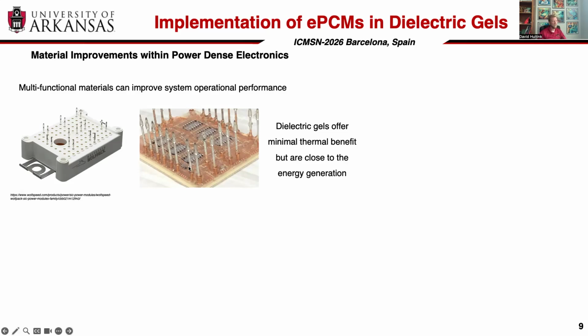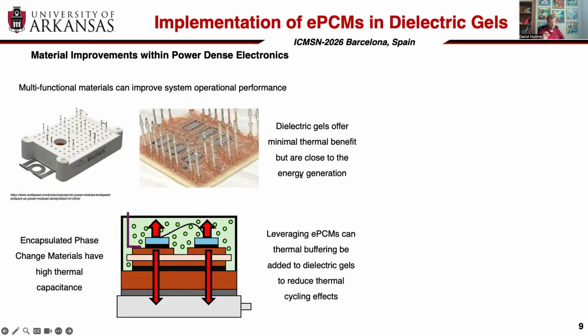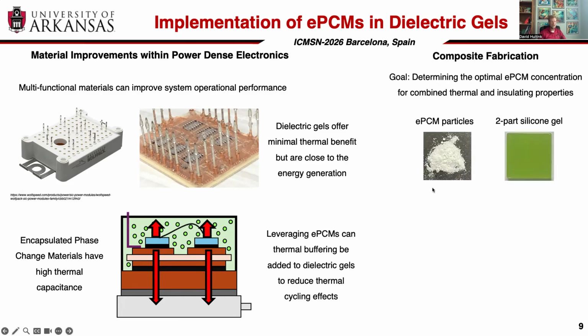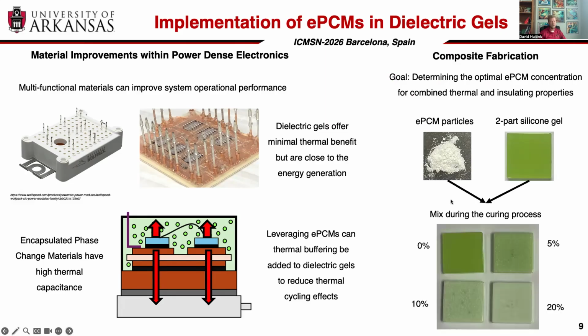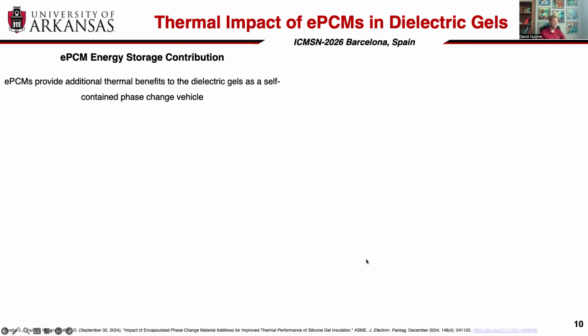And so in power electronic systems, often we use an encapsulating silicone to provide voltage isolation, but that also is at the detriment of thermal performance because essentially it becomes a blanket for those devices. So while it's isolating the voltage, it is also contributing to higher temperature events. And so if we can integrate ePCMs into the silicone gel and maintain the voltage isolation function, but also be able to have thermal capacitance and thermal storage close to the devices itself, this gives us the opportunity for managing those transient temperature spikes. And so what we do is essentially take the ePCM particles that we've synthesized and mix them into a two-part silicone gel at various loadings, and you can see the outcomes of that here.